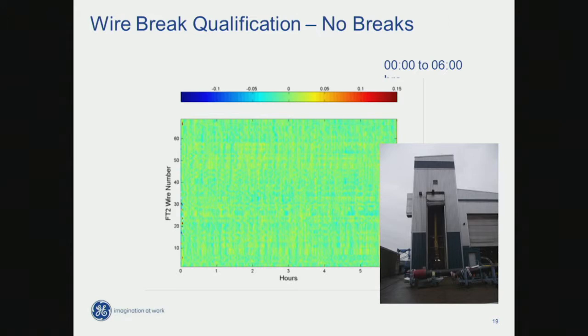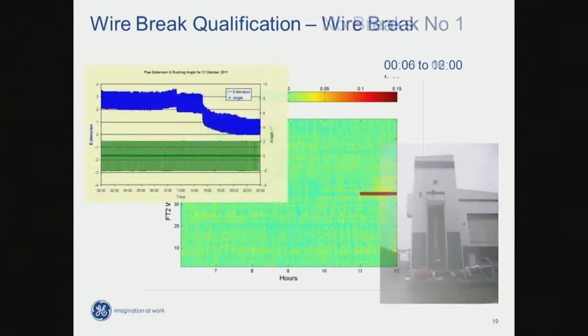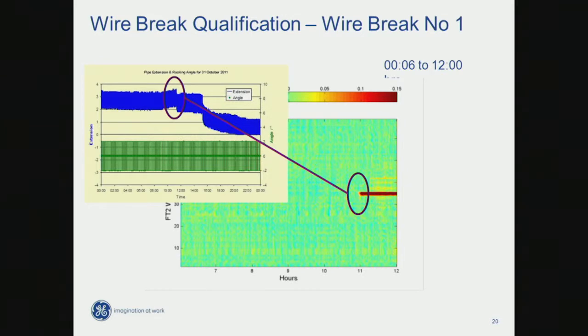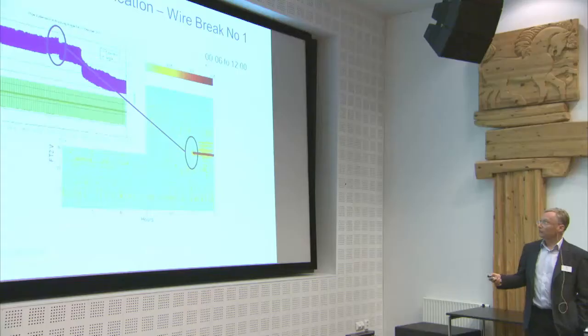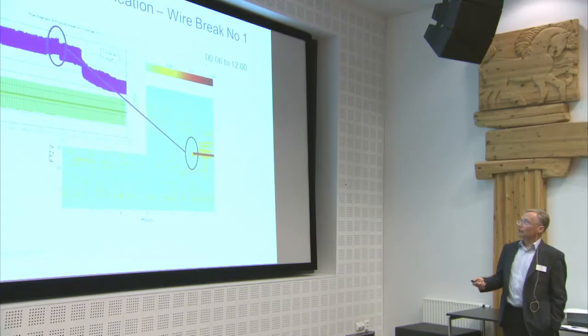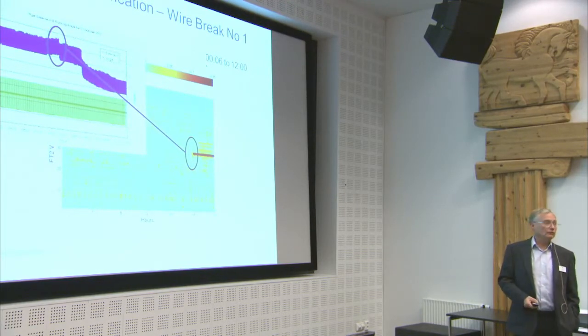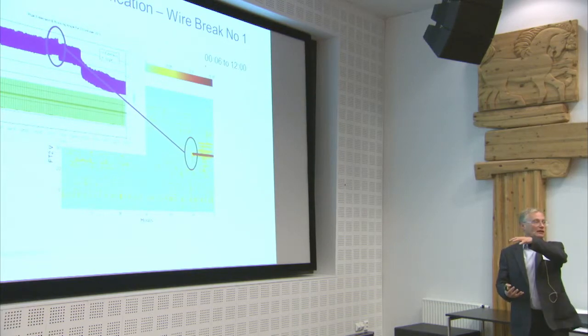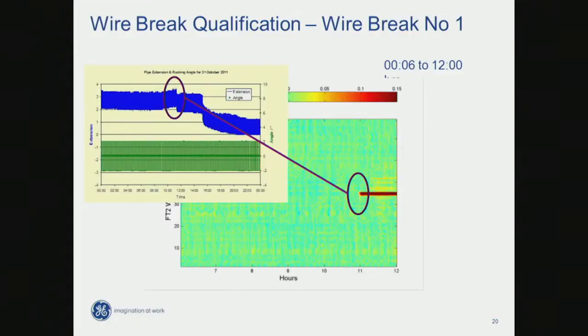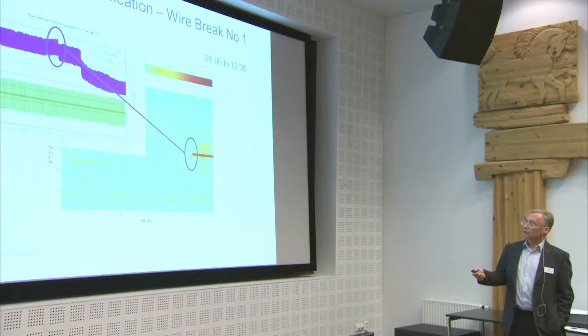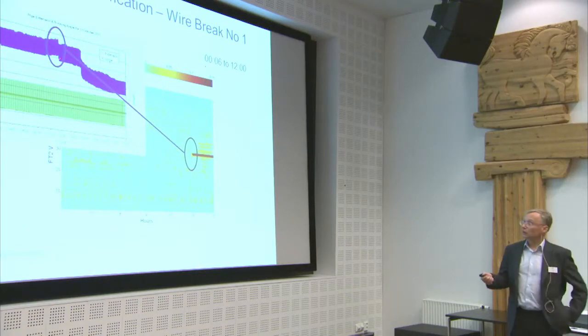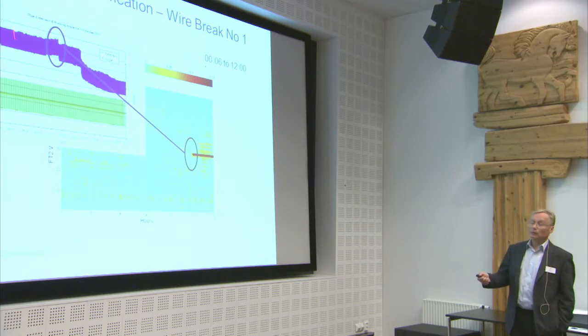But moving it on, what you have is at this time, at about 11 in the morning, a sharp reduction in stress, which is indicative of wire break. So we find the wire break. And what you can see, this is an independent measure from the transducers on the test rig, which is a measure of the axial length of the riser section. And this oscillation is due to the movement of the riser because it's a fatigue test. And at this time, you have a discontinuity in the axial length, which corresponds to a wire break. So we've got alignment of those 2 times, and we delivered this result before we had the benefit of that.